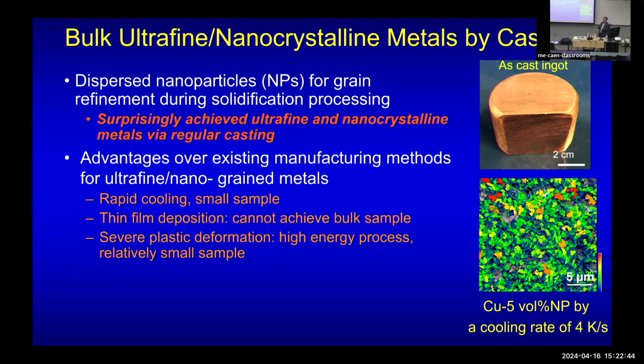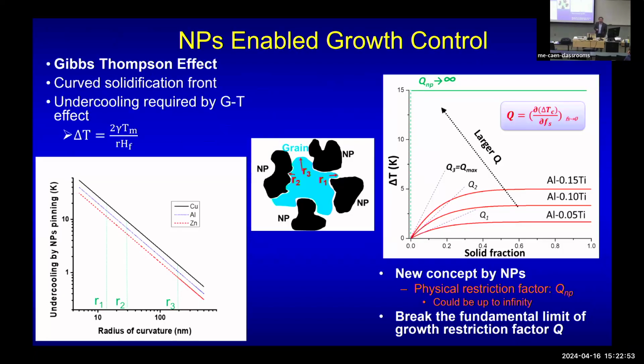So this really shocked us, because we thought it was impossible, but now it has been made possible. That allowed us to study why it happens. Actually, we found out that what is more important is nanoparticle-enabled growth control, basically restriction of the growth. It's not about nucleation. In the early days, people said that more nanoparticles give you more nucleation. No, it's not like that.